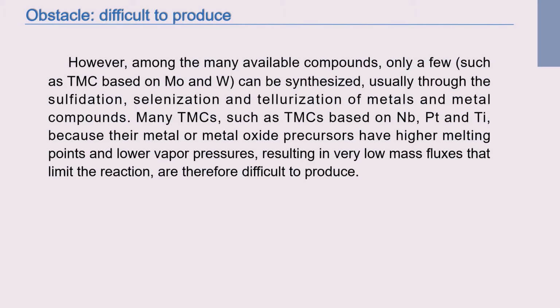However, among the many available compounds, only a few, such as TMCs based on molybdenum and tungsten, can be synthesized, usually through the sulfidation, selenization, and tellurization of metals and metal compounds. Many TMCs, such as TMCs based on niobium, platinum, and titanium, are difficult to produce, because their metal or metal oxide precursors have higher melting points and lower vapor pressures, resulting in very low mass fluxes that limit the reaction. So in this case, many different methods are used to solve the problem of difficult production.